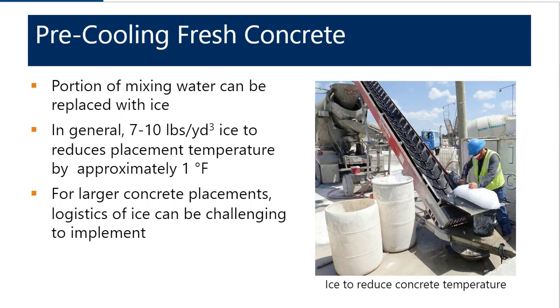The thing to keep in mind here is for larger concrete placements, the logistics of adding ice to a truck can be extremely challenging to implement. And so you can see the photograph here on the right, where individual bags are being broken down and then conveyed up into the truck. And so you can imagine if we're adding 100 pounds of ice per cubic yard per truck, for example, a 5,000 yard placement, that's a significant amount of ice, not just to obtain, get to the ready mix supplier, but also to load up, get dispersed in the truck, and be able to do that over several hours.